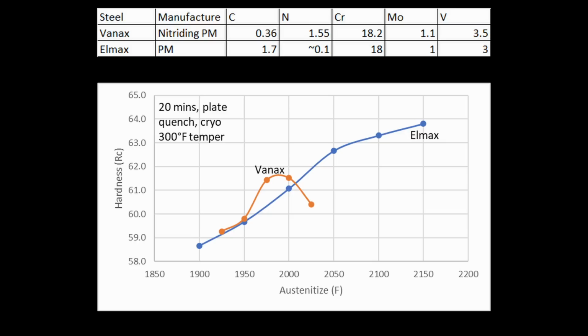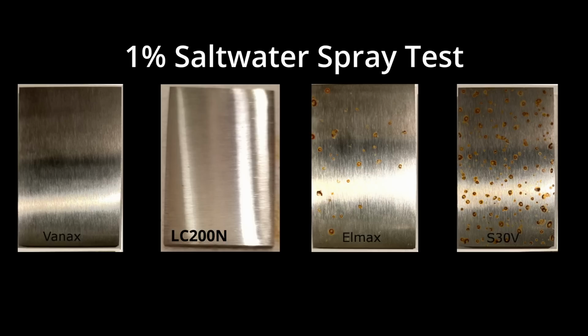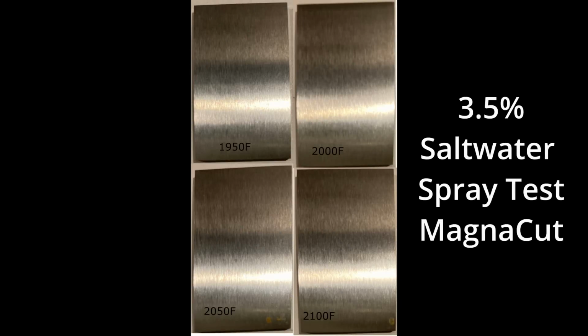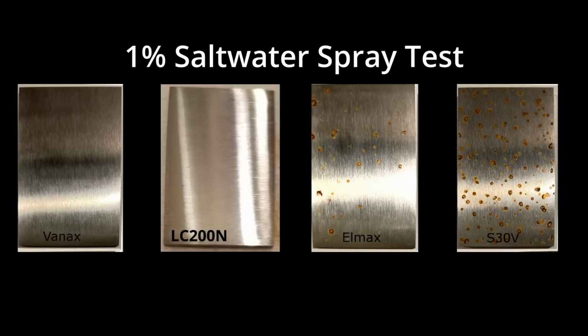Now the Vanax basically tested the best in corrosion resistance compared to all the other steels that were tested. Well, Vanax and LC200N, I couldn't get any rust spots on them in my saltwater testing. So MagnaCut, if I ran 4 or 5 specimens, I might get one that had a little rust spot on it. But for Vanax and LC200N, I never got any rust spots on them.